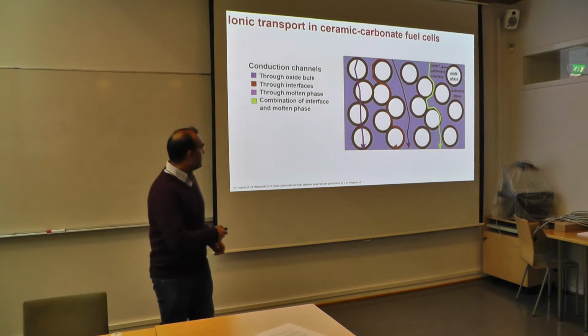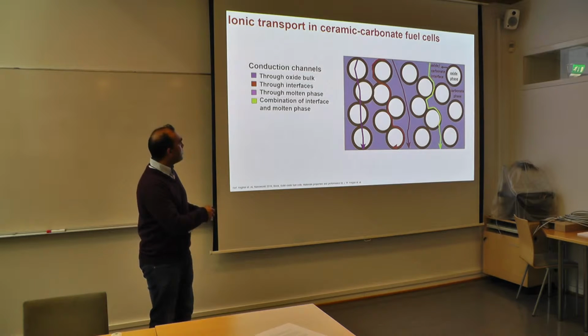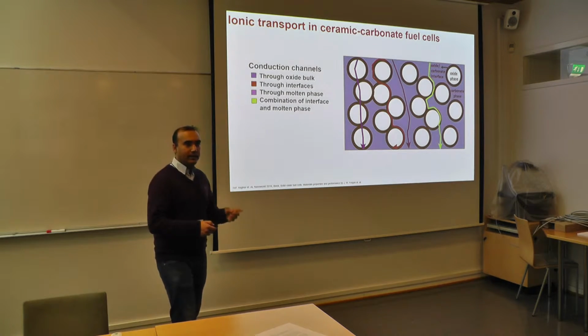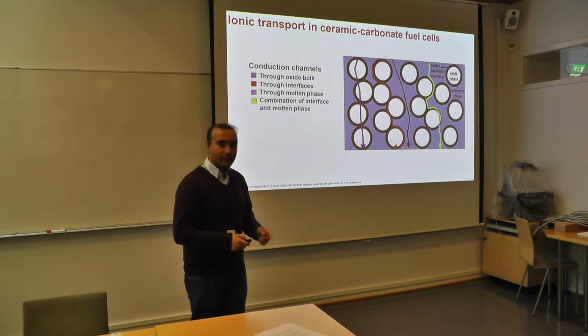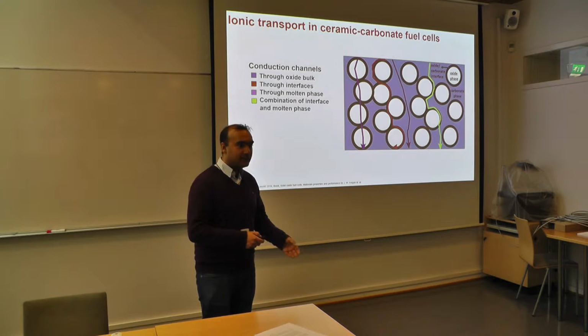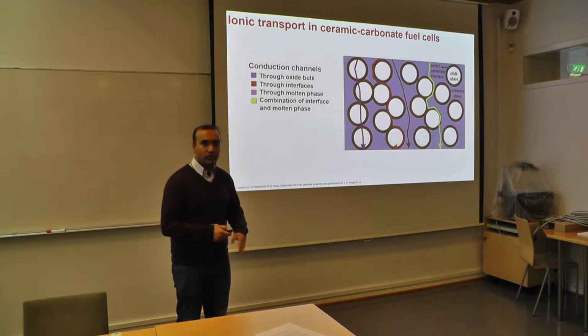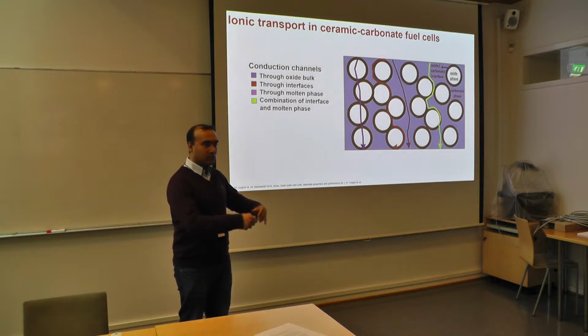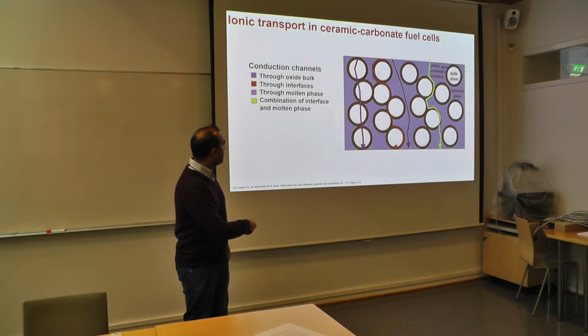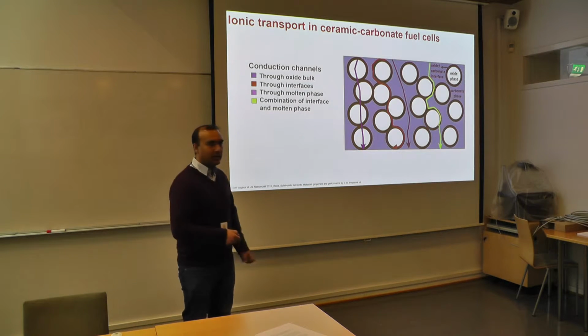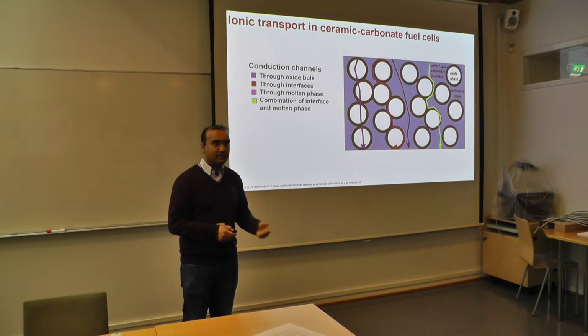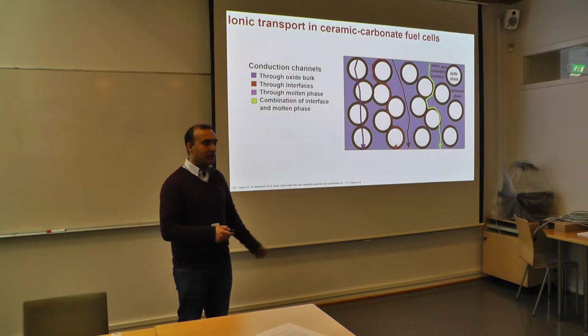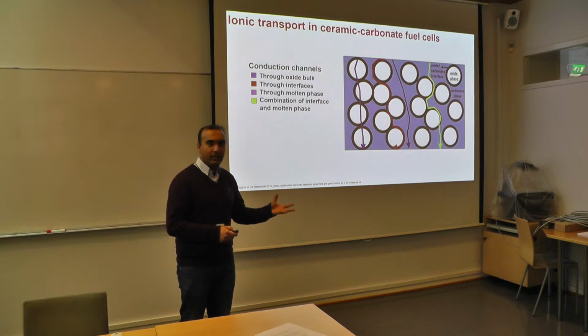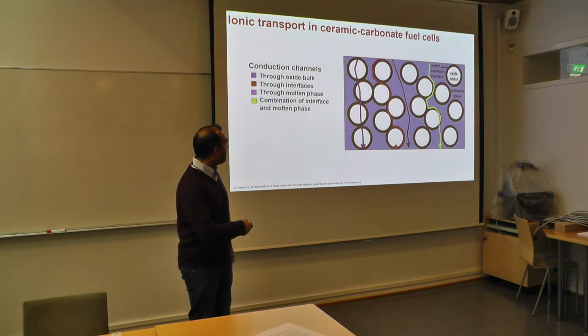Okay, one more thing here. Since it's a composite material, the blue color over here that you see is basically the carbonates. And as I said, over the eutectic temperature, which is over 400 degrees, this carbonate is in molten, liquid form. So here I show it with the blue color. And these white dots that you see here are our metal oxides, like ceramic material, gadolinium cerium oxide, or any ionic conductor which is metal oxides.